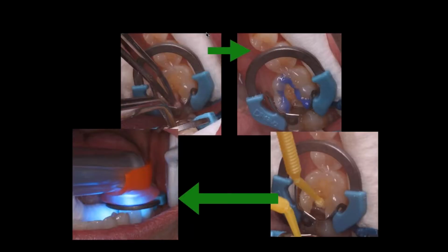Here a selective etch technique was used, carefully applying the 35% phosphoric etch gel for 15 seconds. We're going to nicely rinse that for 10 seconds, continually keeping the entire preparation moist. We're going to do a chlorhexidine blotting pellet, lightly suction that off, and then apply our adhesive, and in this case I'm using Prime and Bond Elect Universal Adhesive.